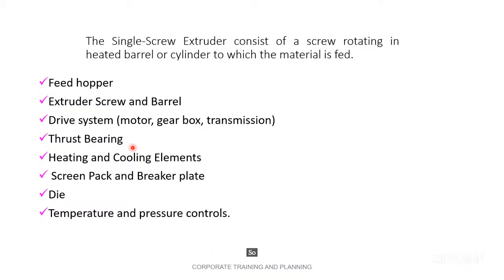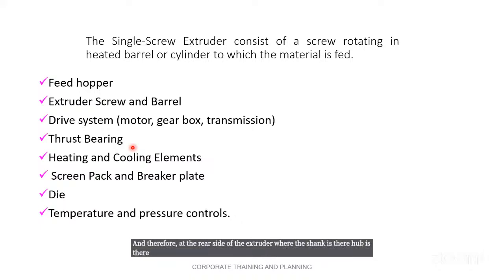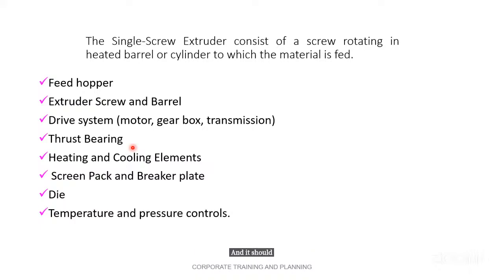So what is its function? It will take the axial load when the screw rotates, and the radial load, because you are passing the material inside the barrel and it is a viscous material. Therefore, a lot of torque is developed inside by the rotation of the screw with such a viscous material, and that load gets developed at the rear side of the extruder, where the shank and hub are, and a lot of pressure is developed there. It should be accommodated, friends. Otherwise, there is a possibility of bending of the screw.